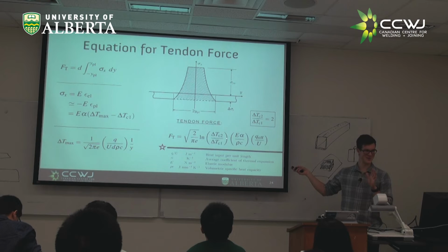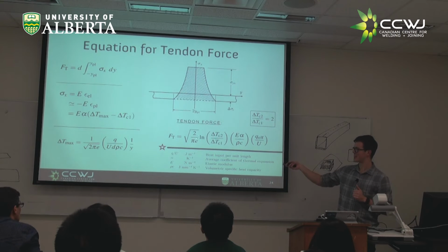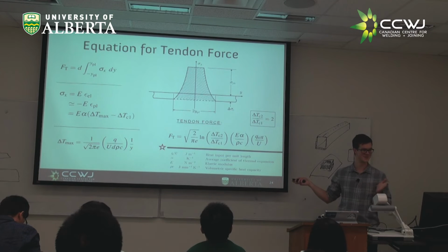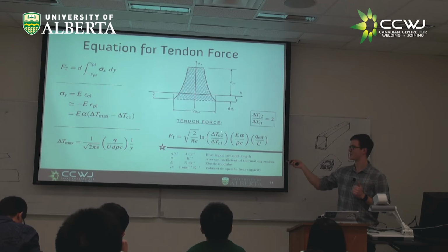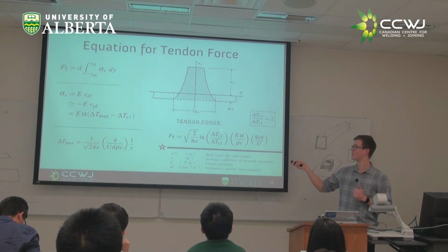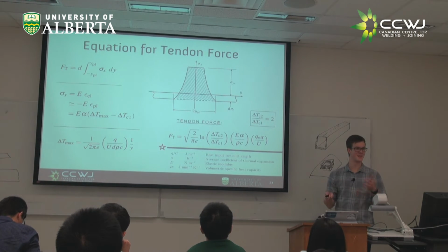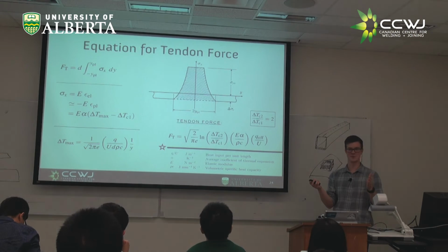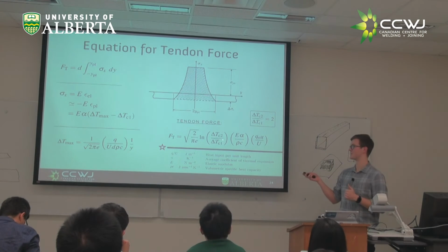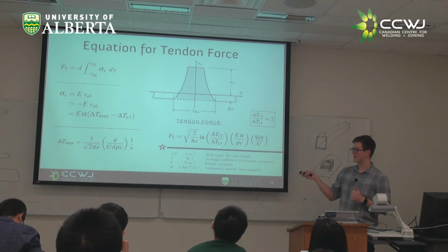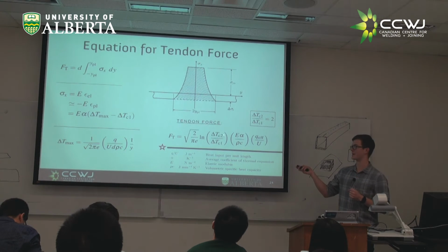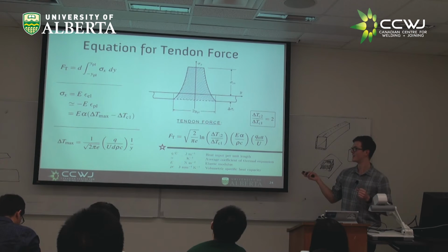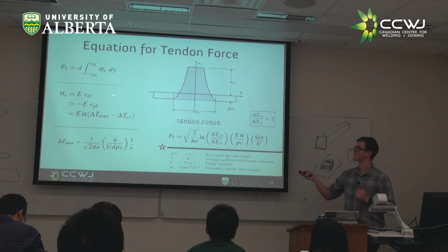Now, stay with me for a minute here. First thing, we end up with a logarithm, and the ratio of our temperatures. Now, I told you that we're not going to have to worry about exactly what those temperatures are, but just the ratio. That's because when we integrate, we get log of one temperature minus log of the other temperature. We can make it the ratio of the temperatures. So although we know that this is about 80 degrees above room temperature and this is about 160 degrees above room temperature, really all we care about is the fact that those are 2. And if it's always approximately 2, we don't even have to worry about it.